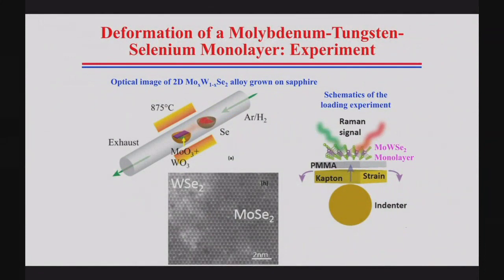They took this material and deformed it, applied strain on it. Cracks developed and began to propagate in the system. They had these kinds of images when the cracks were propagating. They came to us and said, this is what we see. Can you model it? And so we took this information from experiment and started to model it. I will show you the modeling part.